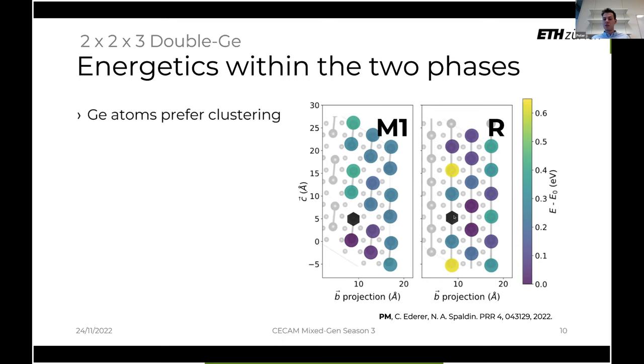The same is true in the rutile phase, where we see this behavior happen in the neighboring chains. So if this position is occupied by a germanium and this position is occupied by germanium, we have a low energy configuration.